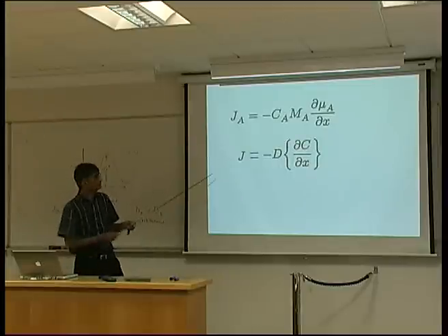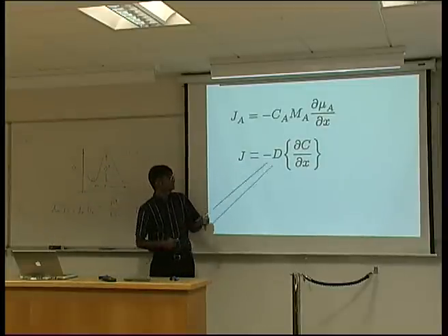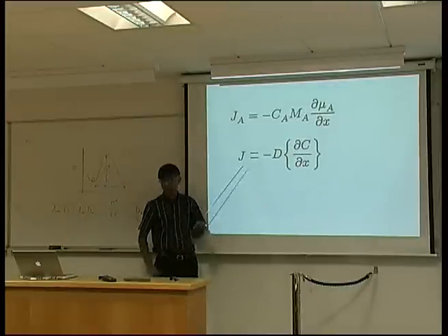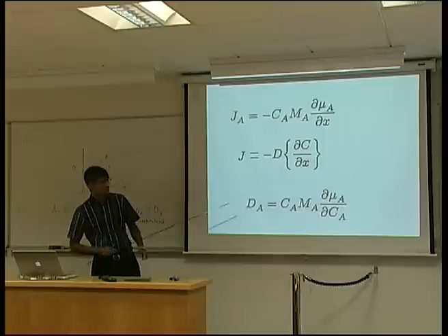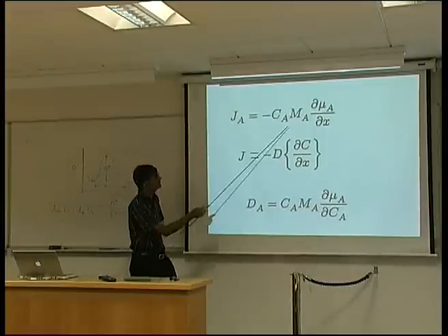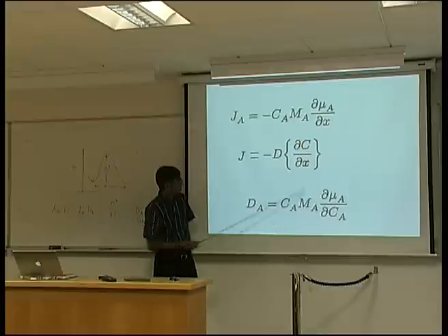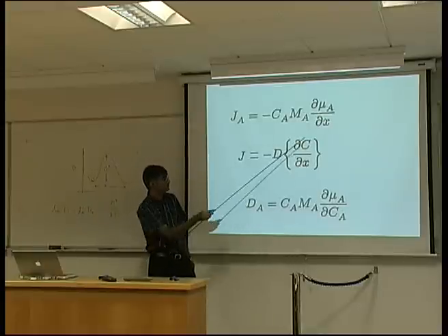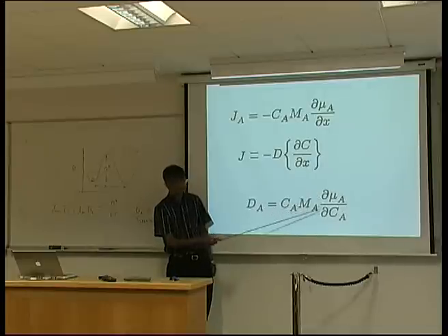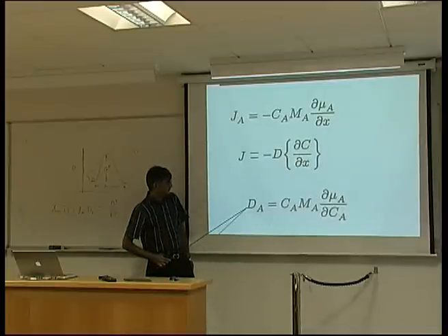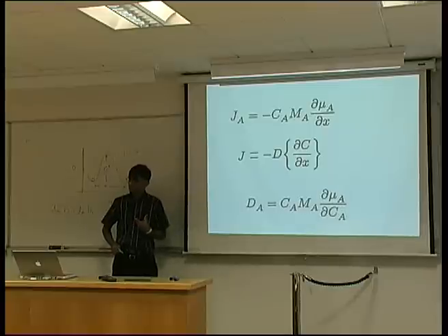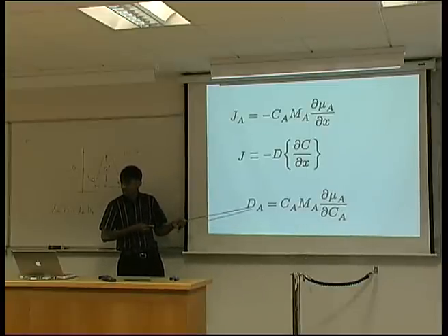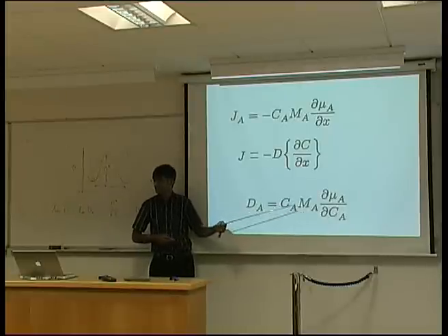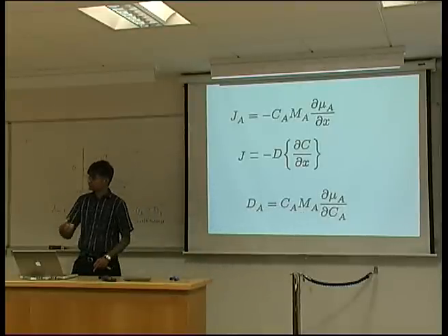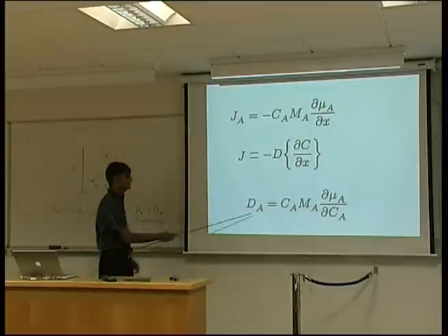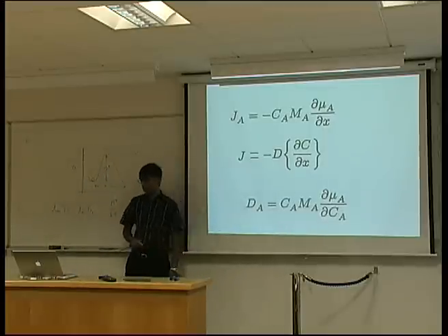And if you compare that with Fick's first law, so here we have chemical potential gradient and here we have concentration gradient, then we can derive a relationship between D and the mobility here and the gradient of chemical potential with respect to x, and this is how the chemical potential varies with composition. So we can use our thermodynamic theory to see how that diffusion coefficient will change with concentration. So the diffusion coefficient now becomes a concentration-dependent term. And if we express it like this, then we can still use Fick's first law to deal with diffusion theory.